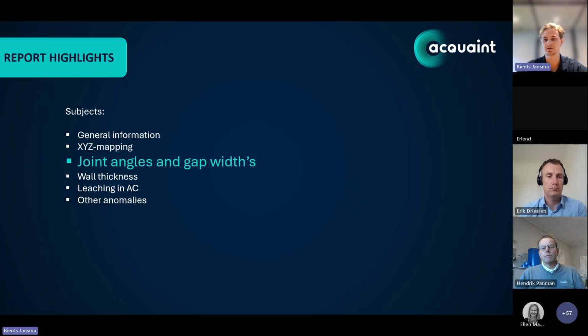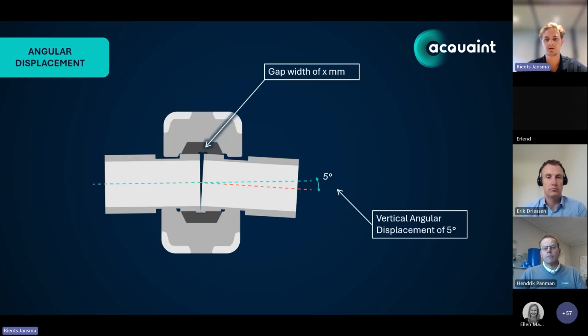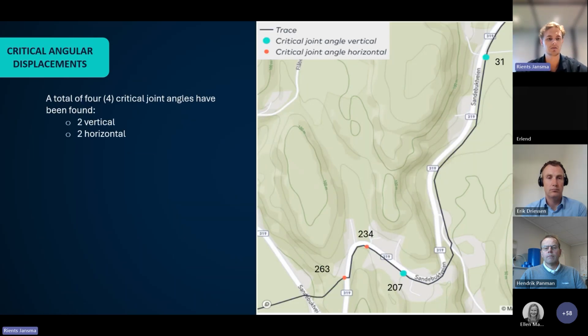Okay, over to the joint angles and gap widths. Like Hendrik also explained a little bit, here's a picture, and here you can see a gap width of X millimeters. On the right side, you can see the vertical angular displacement of 5 degrees. So from the point you have horizontally, and then it goes down a little bit. In total, we've found 4 critical joint angles, 2 vertical ones and 2 horizontal ones. You can see them here. The numbers at the spots are the ID numbers of the pipe sections we've also implanted in the dashboard.